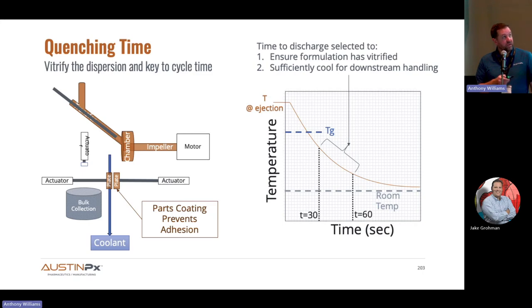We're just taking the material out of the system, cooling it to some practical temperature, and we can start to press this time as throughput becomes important to the process, as we care about efficiencies, as we care about yields. I don't care about that much in phase 1. Not that much in phase 2 either. But for commercial, it can become important. So this becomes a practical thing about throughputs and potentially, yield.